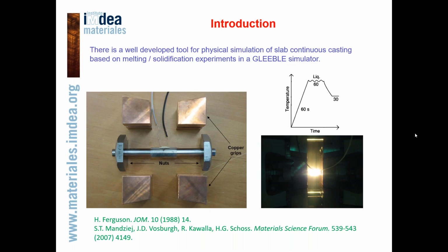It took us a number of tests to find the optimum compression speed to compensate the thermal contraction without damaging the microstructure, and we applied that speed in our experiments.